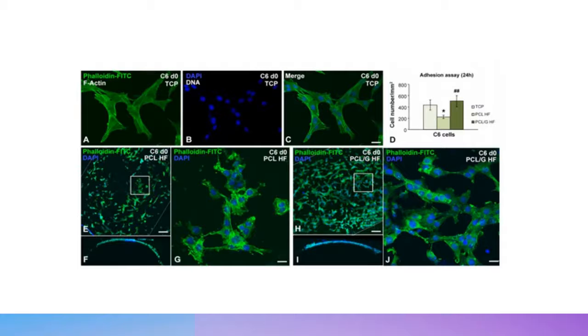Here in Figure 5, representative images of confocal microscopy where the density and cell morphology of C6 cells were observed after 24 hours of seeding on TCP, PCL, and PCL graphene substrate. Cytochemical techniques have also been used with phalloidin, which is the green part, a direct marker of the actin cytoskeleton, and DAPI, which is the blue part for the cell nucleus.